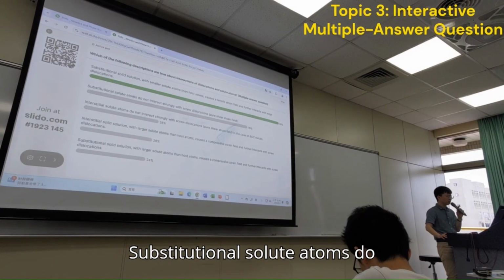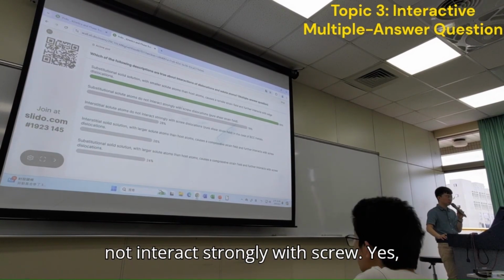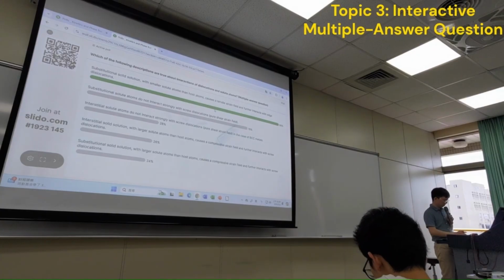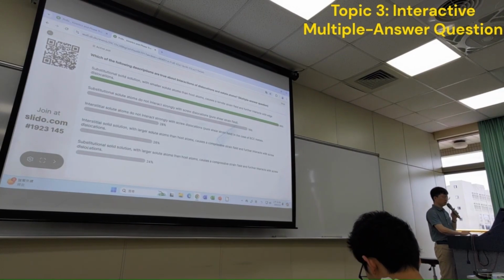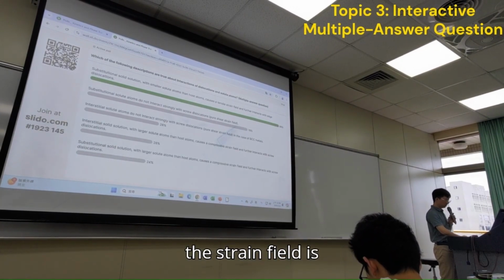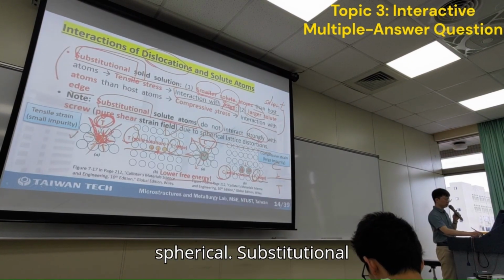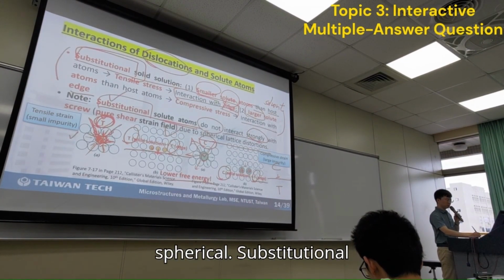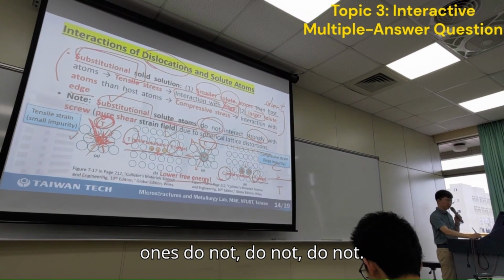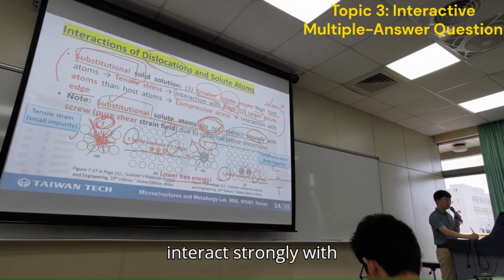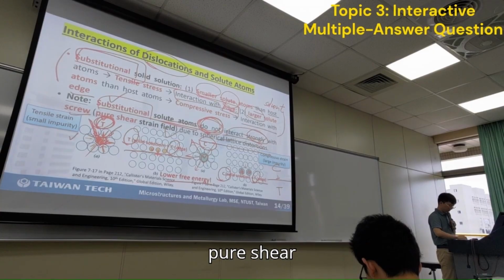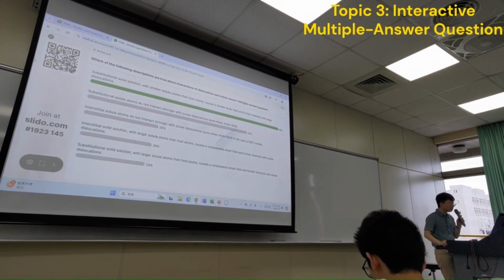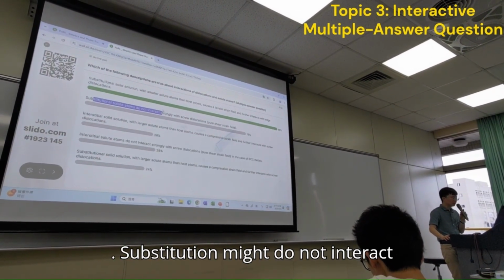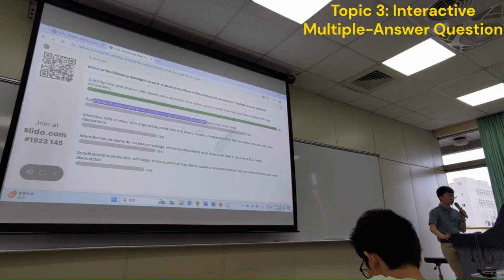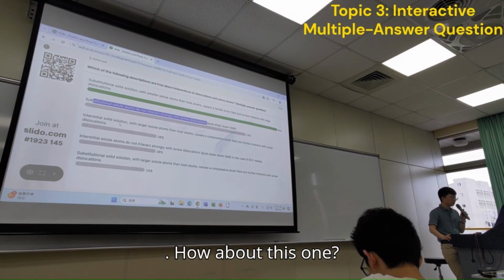Substitutional solute atoms do not interact strongly with screw dislocations. Yes, that's what we just mentioned, because the strain field is spherical. Substitutional ones do not interact strongly with pure shear. Right, substitutional ones do not interact strongly with pure shear. Okay. How about this one?